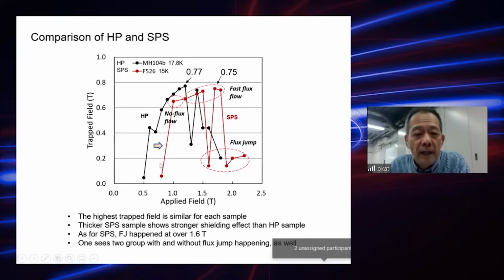So then we must compare the hot press and SPS, spark plasma sintering. The red one is the SPS, and then the black one is the hot pressed sample. The highest trapped field is similar for each other. So then the black one is like this way and goes like this way, and the red one is like this way. So a little bit thicker SPS samples show the stronger shielding effect than HP samples like this.